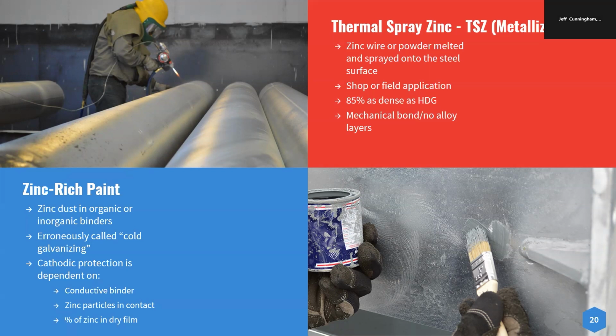Zinc rich paint is zinc dust with organic or inorganic binders. This is often falsely called cold galvanizing. There really is no such thing as cold galvanizing. Cathodic protection is dependent upon the conductive binder, zinc particles in contact, and percent of zinc in the dry film. If you have any zinc-rich questions, you can contact KTA Tator. They usually have some pretty good paint information. Mostly we see zinc-rich paint used as touch-up material on galvanized steel, and we also have huge touch-up material information on the website.